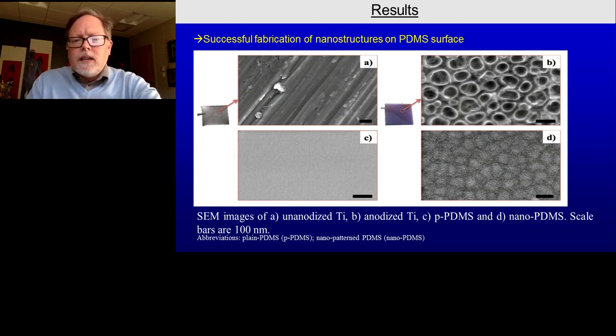And you can copy over the roughness just like any kind of cast mold process that's used in many different industries. And here you see in A is the starting titanium, the nano smooth titanium. The picture right below it is a PDMS copy of that starting titanium. So both are very smooth at the nanoscale. If you then look at B, again, that's our anodized titanium, has all those nice anodized nanotubes, and our PDMS copy of that titanium is in picture D. So we were able to copy the roughness over to the polymer. Again, we followed our equation.